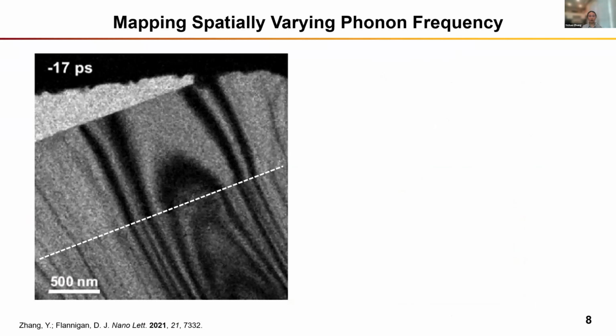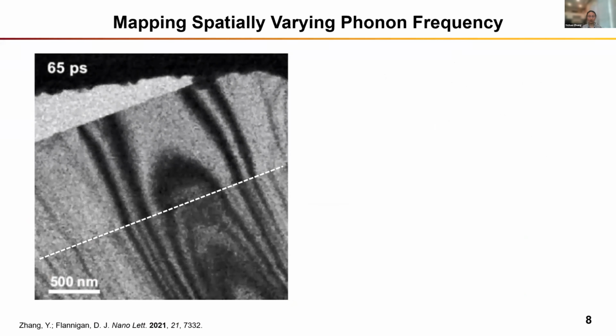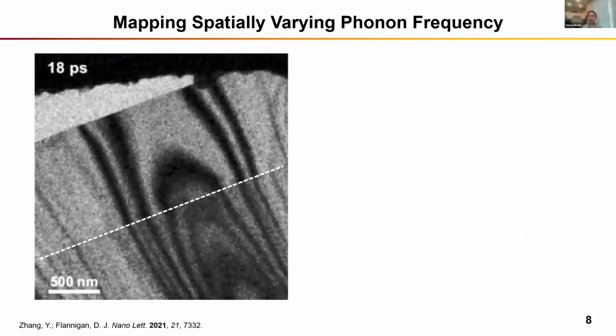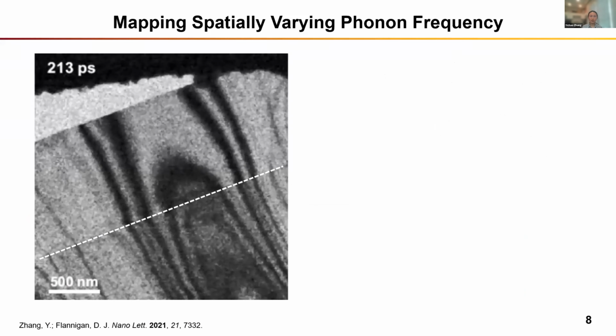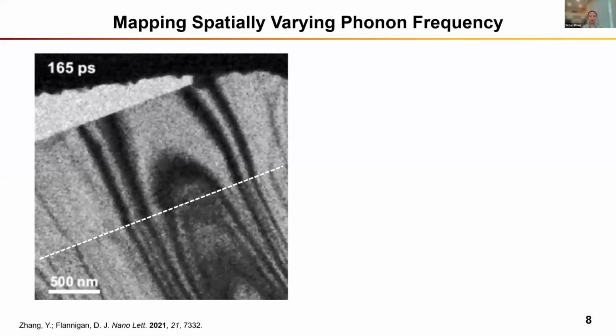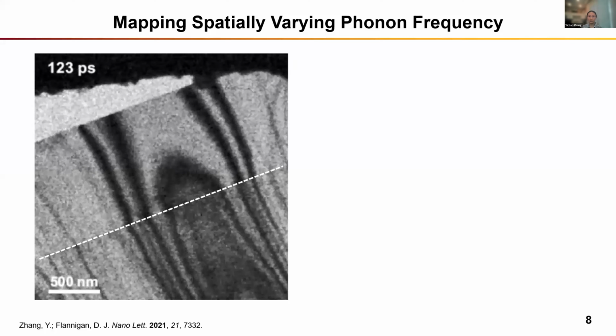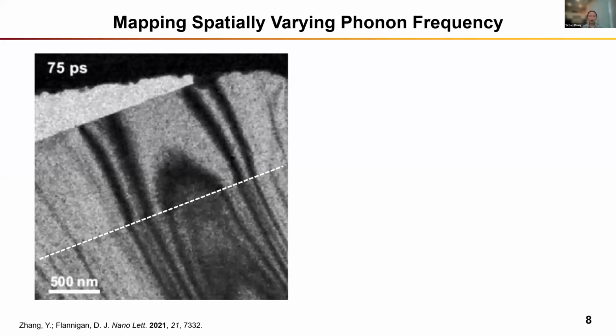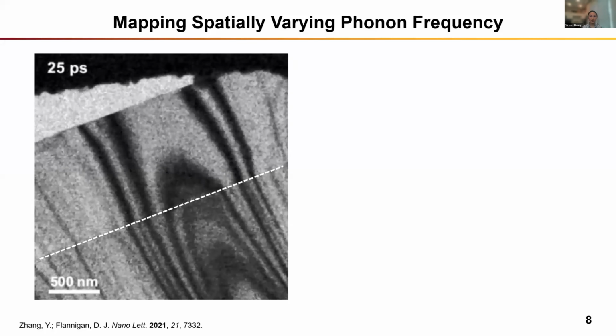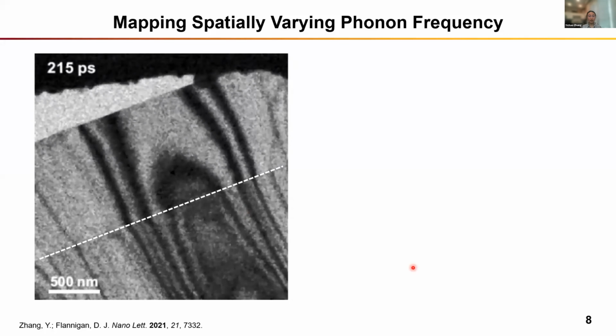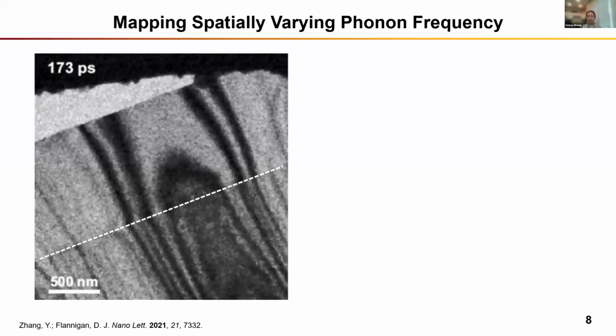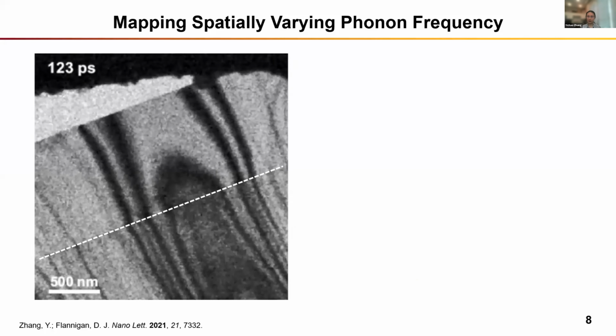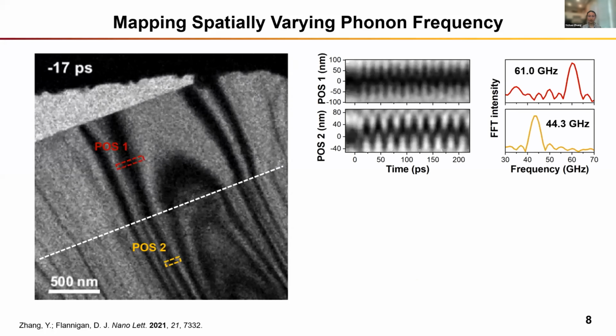So here's a UEM video of the photo-induced z-axis dynamics of another MoS2 flake, and it is tilted at about 29 degrees. So the dashed line here marks the position of a step edge that is about 10 nanometers thick. So in this video, we can see a shearing behavior of the bend contours in the 2 different regions separated by the crystal step edge. Within each region, the oscillation is quite coherent, but things seem to be more complicated at the step edge. So of course, we can quantify the oscillations by generating a space-time contour plot and taking the FFT of the oscillation to really get our oscillation frequency.